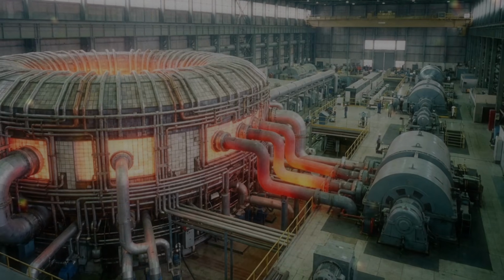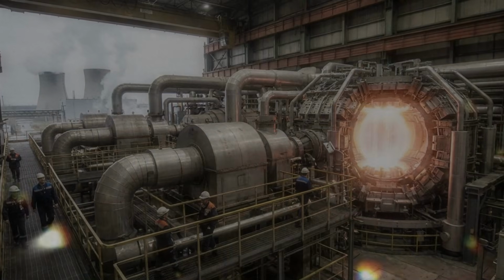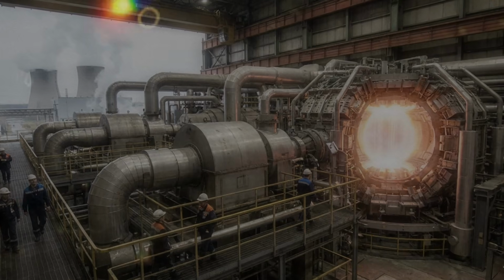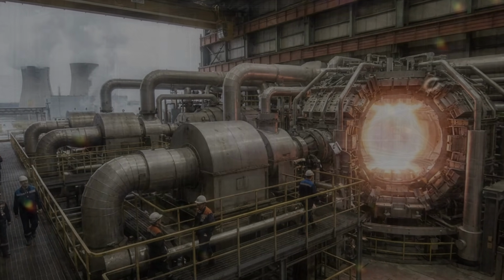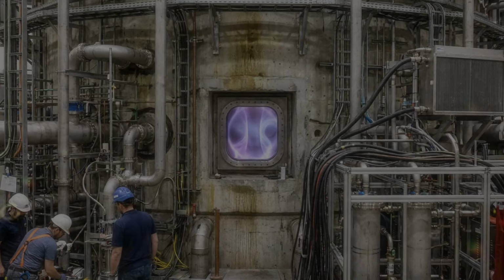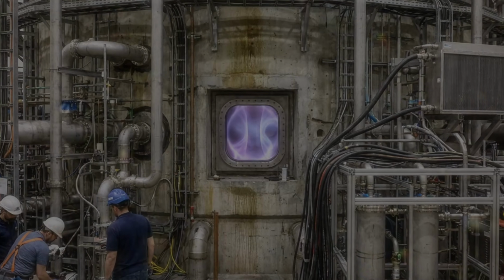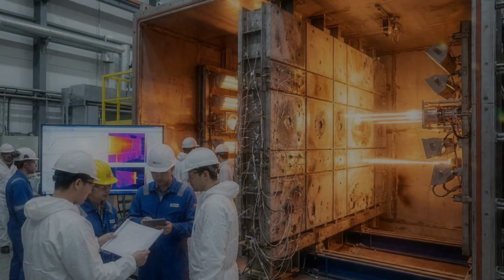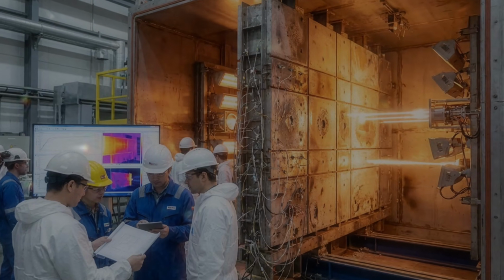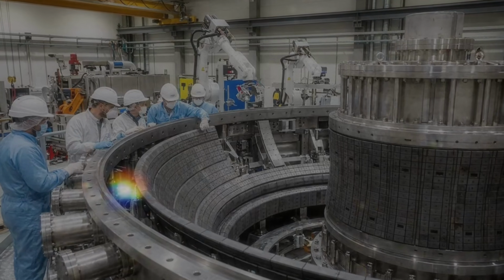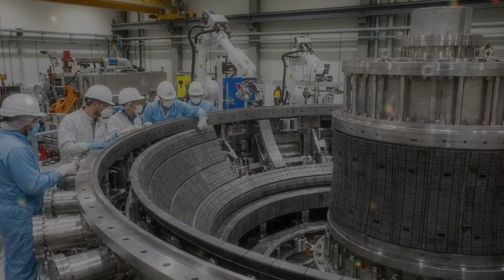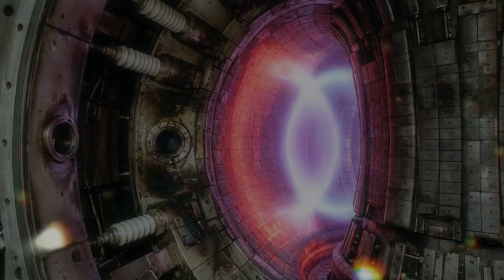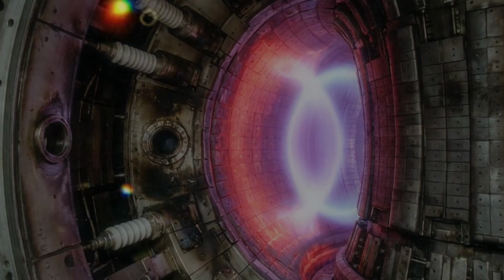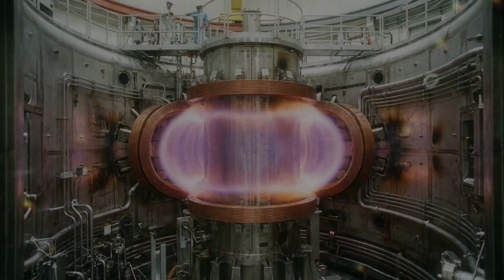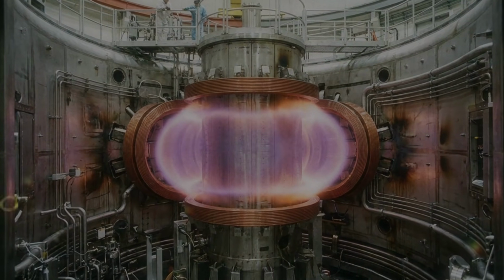One reason boron is useful is that it can help control impurities, especially oxygen. Oxygen in the plasma can be troublesome because it radiates energy away. In a fusion machine, every unwanted radiator is a thief of heat. The plasma needs to stay hot, and impurities that carry energy away can make that harder. Boron has a talent for binding with oxygen and other impurities at the surface, reducing how much of them enter the plasma. When the walls are coated with boron, the plasma can become cleaner. Cleaner plasma often means better confinement, lower radiation losses from unwanted atoms, and improved performance.